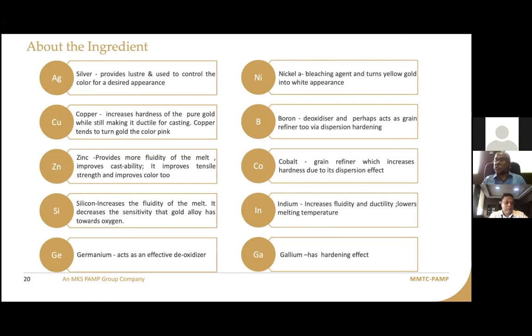While indium is a low melting element, which is added for improving the fluidity and ductility. It lowers the melting temperature by forming a very low melting phase and helps in improving the fluidity. It has to be added in small quantity, and especially it is applicable where you want to substitute the cadmium in case of solder alloys, because cadmium is banned. So you can use indium to make solder alloys as a substitute of cadmium. But it is again a little on the costlier side. You need to be careful about that.